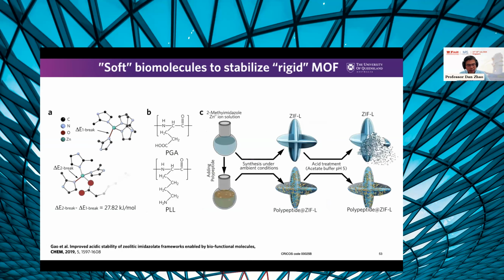That work reminds me of CALF-20. You're familiar with CALF-20? This is a MOF reported by George Shimizu's lab, and this material has extremely high stability towards not only water but even steam, so that BASF and Svante scaled it up to, I believe, close to ton scale for carbon capture, where you use a temperature swing to regenerate the material. In the structure of CALF-20, the inorganic part is a four-coordinate zinc with 2 oxygen and 2 nitrogen. So it's probably because of the mixed coordination of both nitrogen and oxygen that makes the material extremely stable.